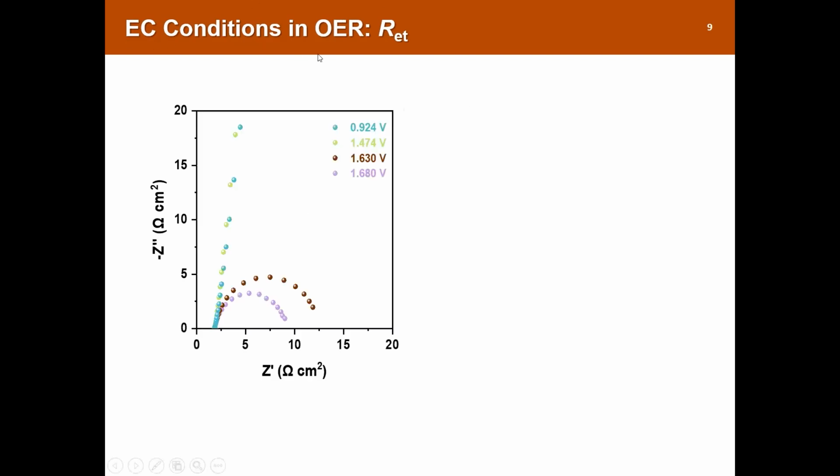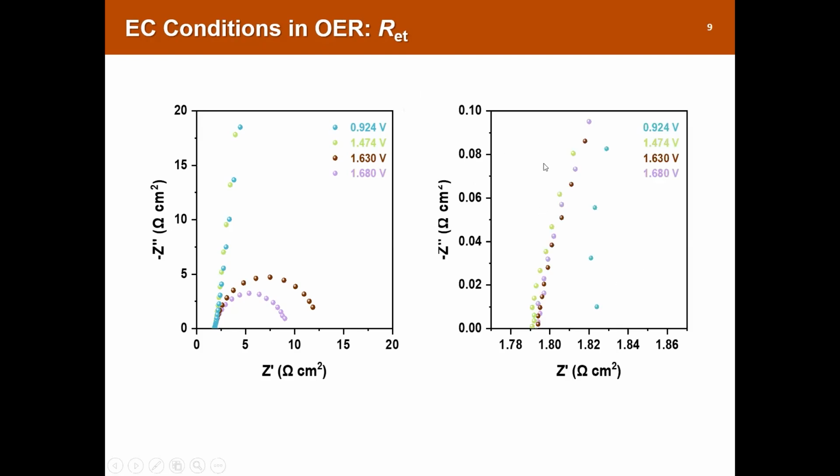And also, electrochemical testing condition can affect the RU value. So we have electron transport resistance. For example, OER catalyst material like nickel hydroxide is insulating. But before the OER, we go through the anodic redox reaction and form nickel oxyhydroxide. And nickel oxyhydroxide acts as the OER catalyst. But during that redox transformation, conductivity of the catalyst layer changes. Nickel hydroxide is super insulating. Nickel oxyhydroxide is a conductive, semiconductive material. So it's actually detectable using potential dependent impedance analysis.